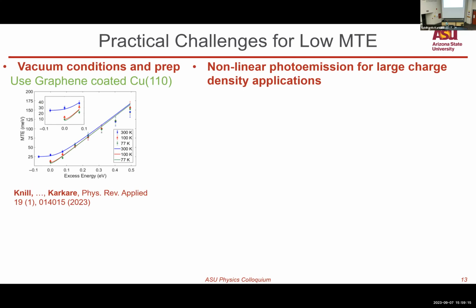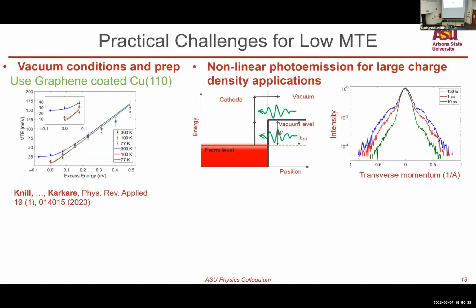And we were able to measure the same small mean transverse energies from this surface. And it also lasts for a long time. It's not very stringent with regards to vacuum condition. So that's a fantastic development. The other issue is nonlinear photoemission. When we emit right at the photoemission threshold and further cool it down, we take a big hit in the quantum efficiency. That's the number of electrons emitted per photon.